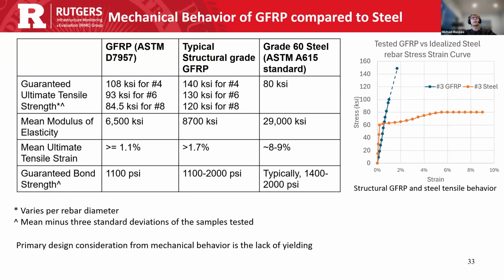So there is that standard, ASTM D7957, that sets the minimums. So these are fairly low. This was implemented a while ago. The technology seems to have improved a decent bit. And the typical structural grade GFRPs that are used currently in infrastructure projects are fairly significantly stronger. They have high modulus of elasticity compared to the earlier bars, better ultimate tensile strain, guaranteed bond strength that, from what we can see from literature, is approaching that of steel.